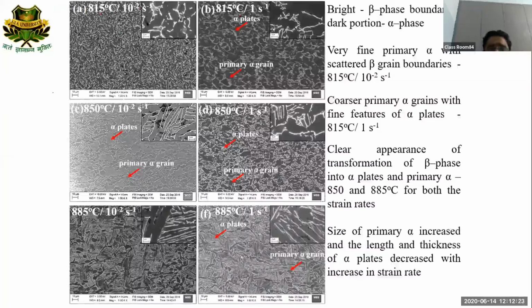This is the 815 degree, 1 strain rate sample. It is 815 at 10 to the power minus 2, 850 at 1 strain rate, 885 at 10 to the power minus 2, and again 885 at 1 strain rate. So these are the features of the cell. Here you can see these black domains are known as the alpha phase and the bright lines are known as beta phase boundaries. Okay. So as you increase towards the beta phase, which starts from 900 degree centigrade, the beta phase boundaries increase and reduce the domain of alpha phase.